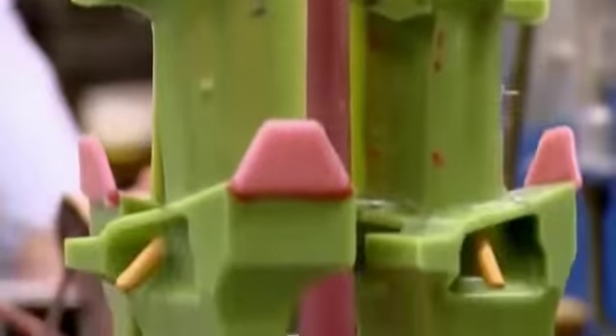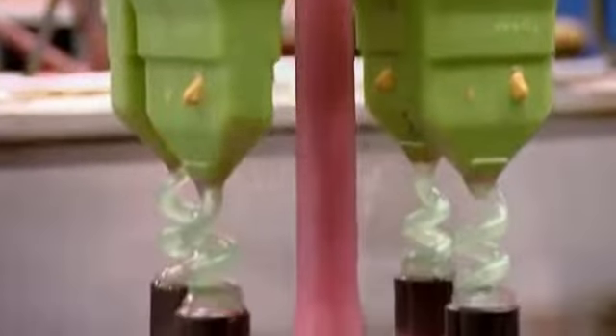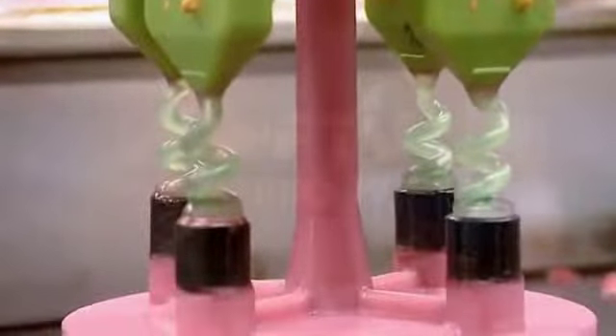The secret part is the way the molten metal is cooled through a spiral tube at the base of the mould. The tube prevents all but one crystal of solid metal from passing through, allowing that single crystal to grow throughout the mould.